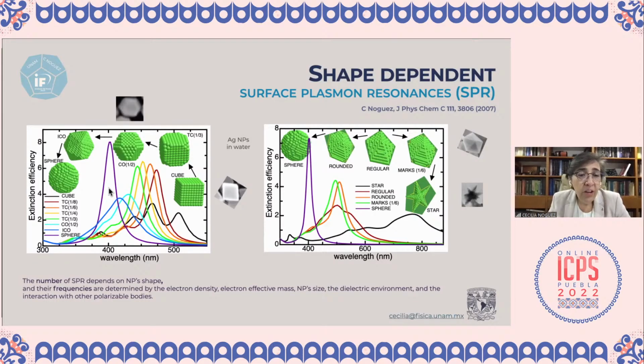However, for example, if you have a cubic nanoparticle, we have, for example, this dark line, the black line, actually, that has 1, 2, 3, 4, and we can see up to 6 different resonances because now we have a different kind of charge distribution on it.